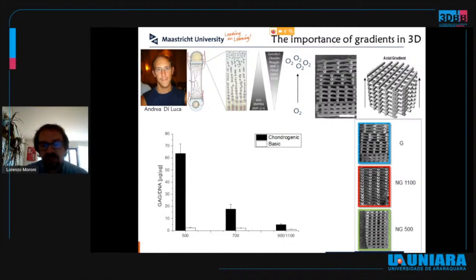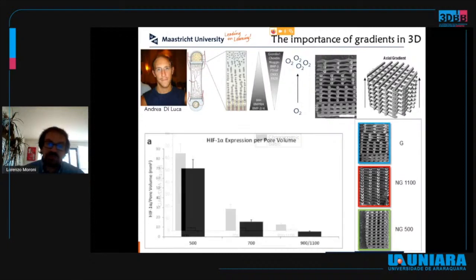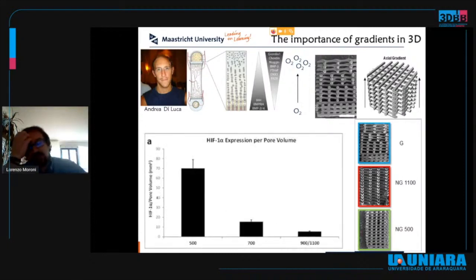This confirms a little bit what was our original hypothesis, that probably with the lowest pore size we have a tendency of having lower oxygen and therefore higher matrix production for cartilage tissue, and in higher pore size we would have higher oxygen concentration, higher nutrient availability, therefore more predisposition for osteogenic differentiation. To further confirm that, we also looked at a specific protein which is directly related to the lack of oxygen, which is called the hypoxia inducible factor.